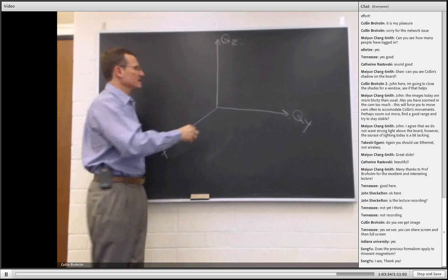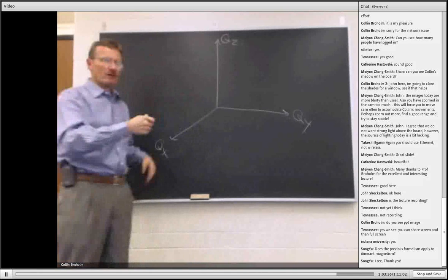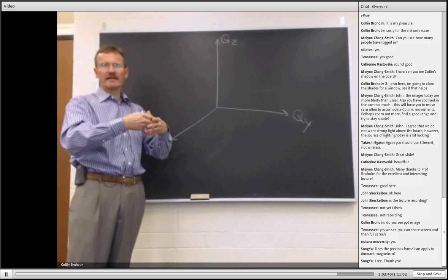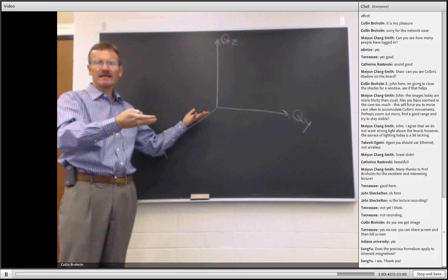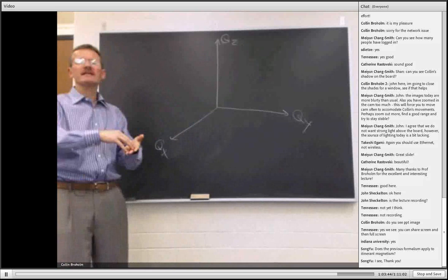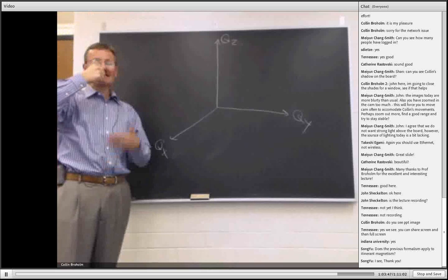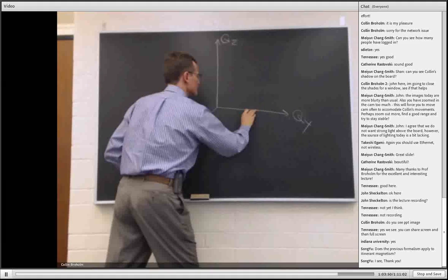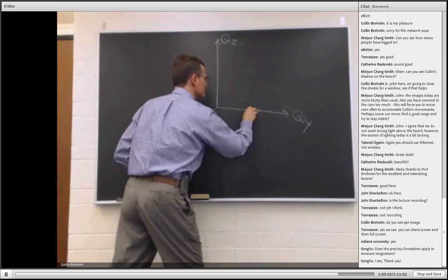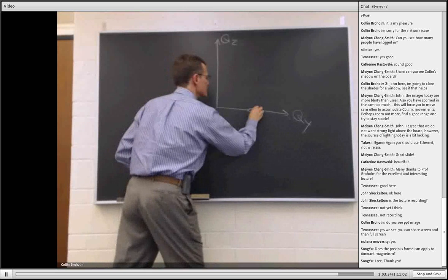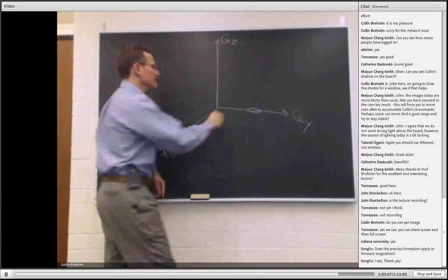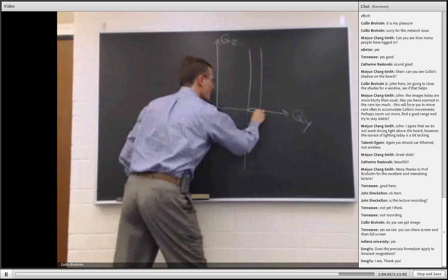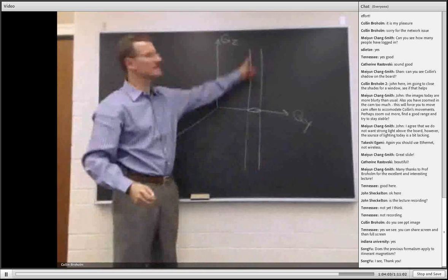That means that even though I have a relatively long correlation length in the Qx, Qy plane, I'm not going to have any correlations in the z direction. In momentum space, what that means is that I'm going to have, let me draw it here, some sort of relatively sharp feature in the Qx, Qy plane, but then this will be some rather long rod of scattering in the z direction.